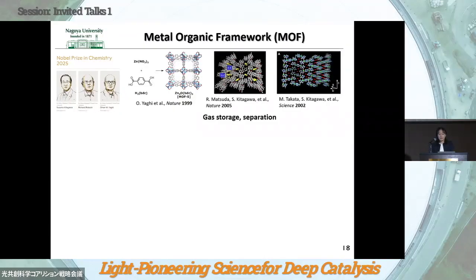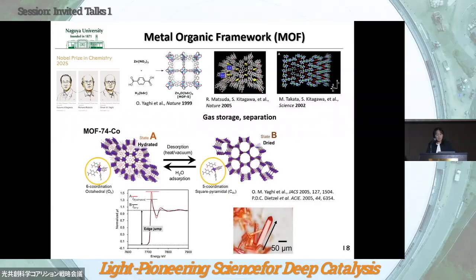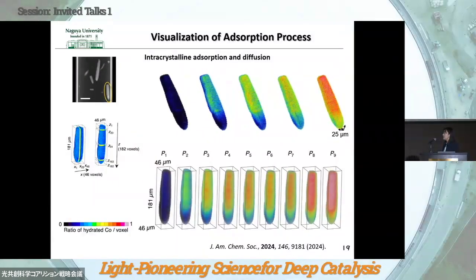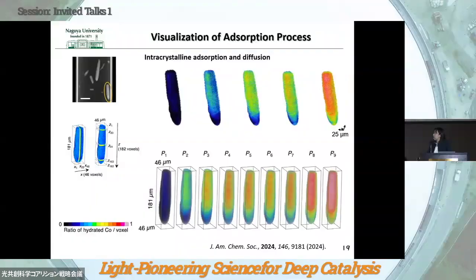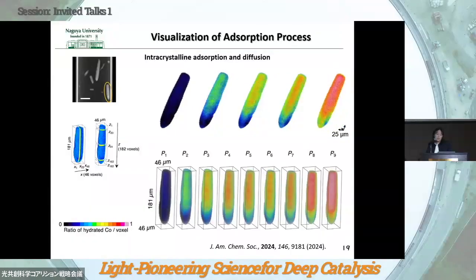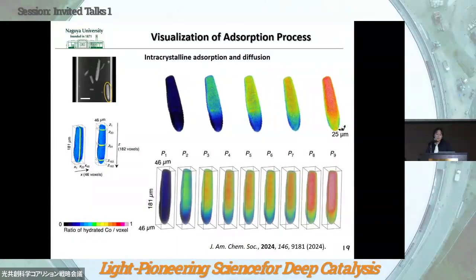We focused on MOF-74, in which adsorption of gas molecules includes changes in the coordination structures of internal metal sites, so the change in the local coordination structure of the cobalt species in the MOF, and investigated how gas molecule adsorption propagates within a single MOF using a density imaging technique. So here, I'd like to show you an example of intracrystalline adsorption and desorption for the water adsorption process.